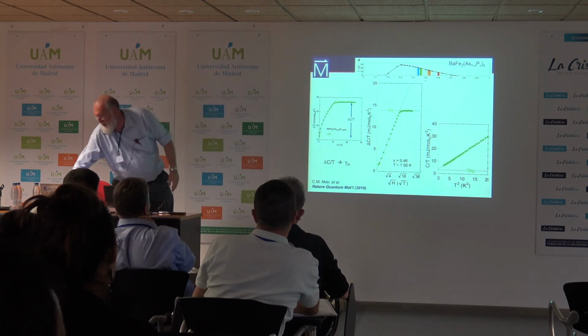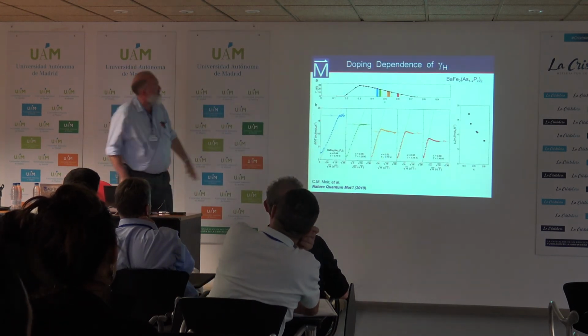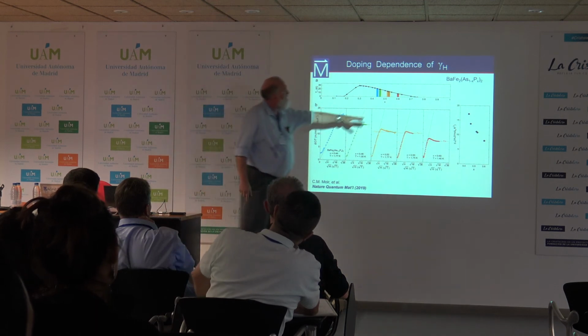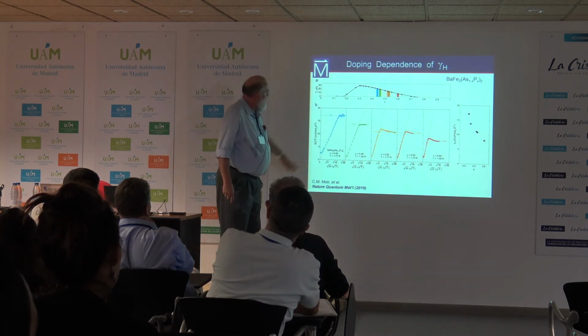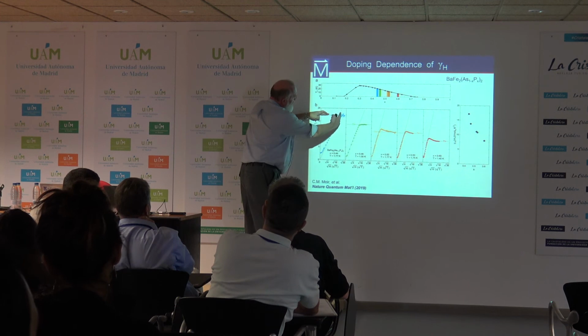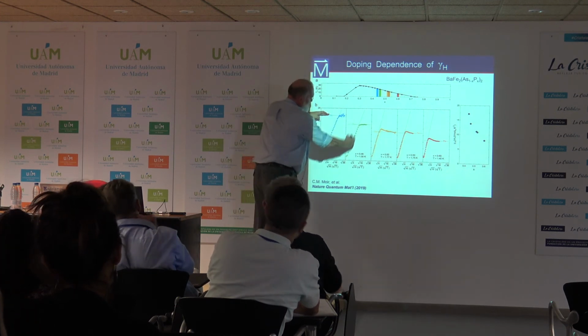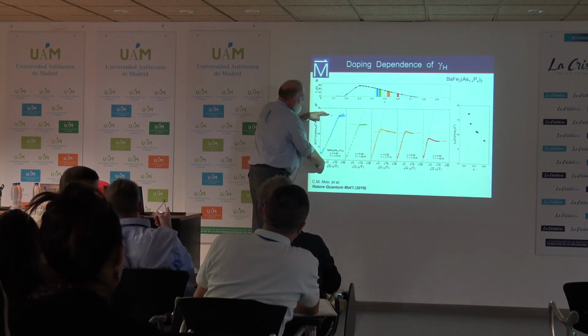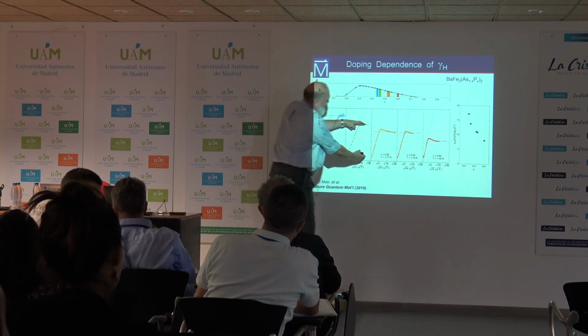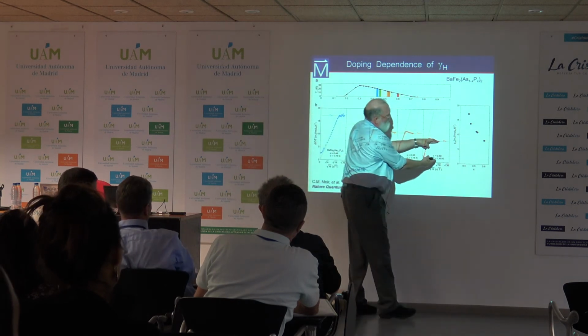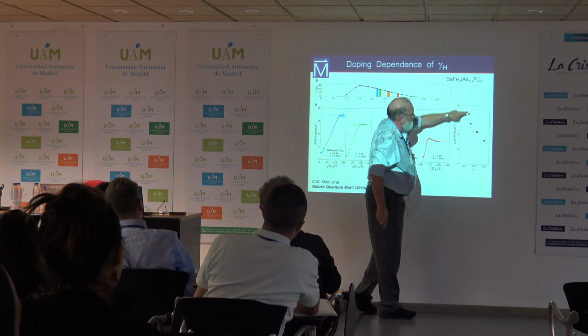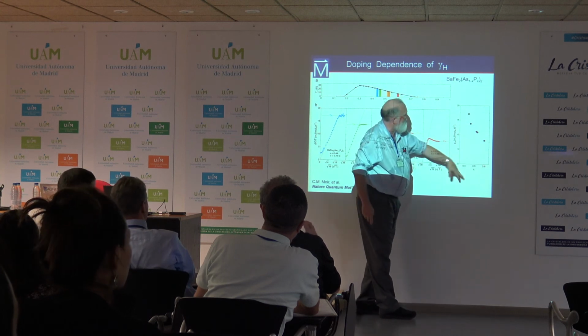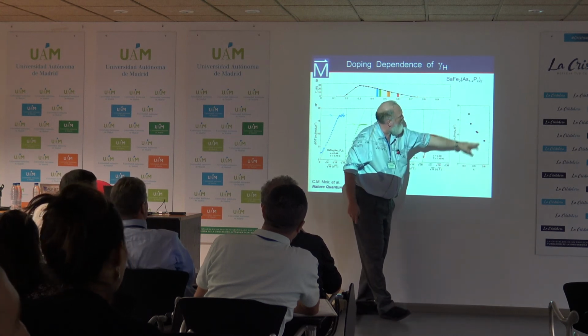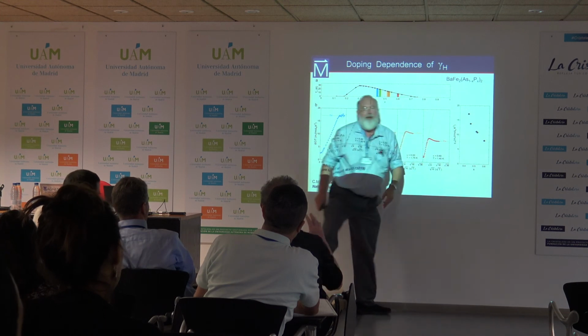And so we'll plot that value of gamma H as a function of doping. These are the 5 different dopings that we can measure. And this value of gamma H, from back extrapolating the linear behavior, the square root of H behavior, clearly has a strong doping dependence, and is plotted here at these 5 dopings going from 0.6 to 0.44. You see that we're doubling roughly the value of gamma H.